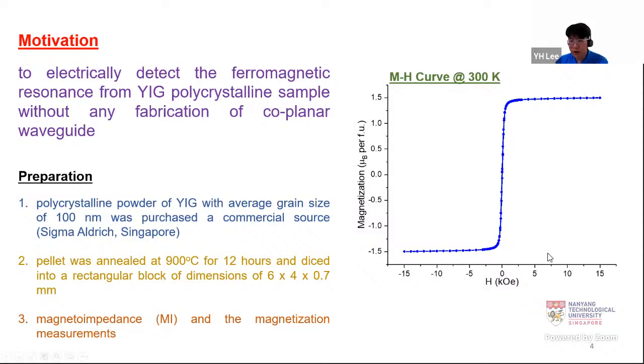So in this case, let me share on the right hand side of this screen, the magnetization curve. As we can see, this is done at room temperature on a VSM Lakeshore. As we increase from low field to high field, we see a sharp increase in the magnetization, and it saturates up to about 1.47 μB per formula unit. And in this case, the coercivity, quite small from this screen, is about 20.7 oersted respectively. The curve we would like to conclude here is that it shows the ferromagnetic characteristics of the YIG at room temperature. After these measurements, and we are assured that this is a ferromagnetic material, we bring it over to